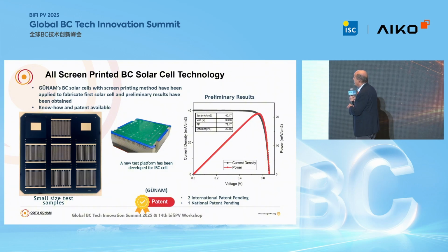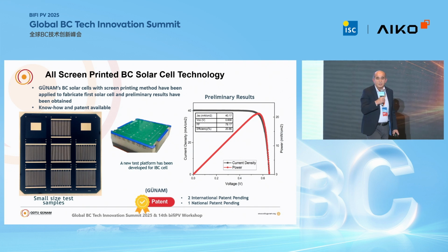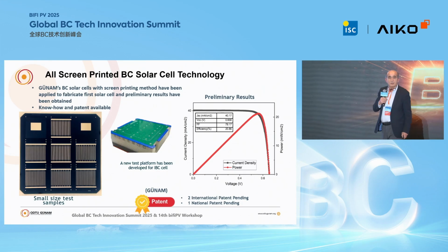Although the efficiency is low here, we have some problems with the fill factor, so it can easily be improved. So we believe that this technique is a strong alternative to the laser approach.